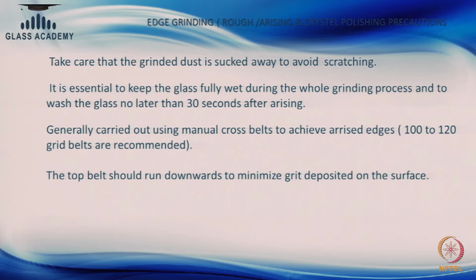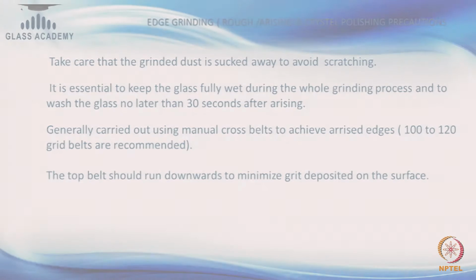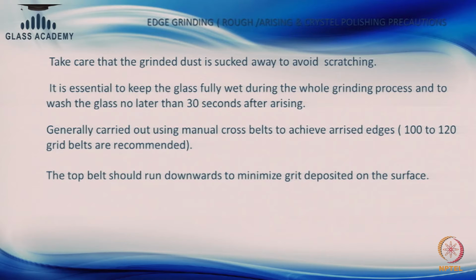Edge grinding, rough arising and crystal polishing precautions. Take care that the grinding dust is sucked away to avoid scratches. It is essential to keep the glass fully wet during the whole grinding process and to wash the glass no later than 30 seconds after arising. Generally carried out using manual cross belts to achieve arris edges. 100 to 120 grit belts are recommended. The top belt should run downward to minimize grit deposited on the surface.